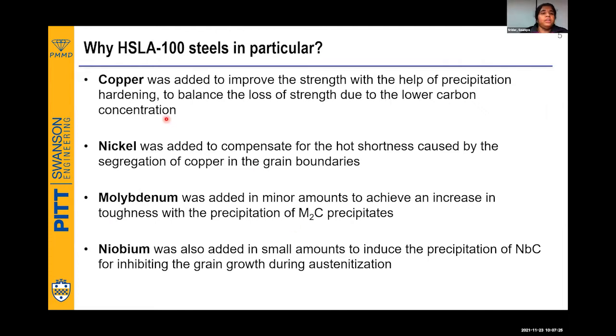And for that, the main addition is copper first. So copper is being added. That's why it's a copper bearing high strength low alloy steel. Copper is going to induce a precipitation hardening by forming pure copper precipitates, or sometimes even called clusters. So this is going to balance the loss of strength due to the lowering of the carbon concentration. Now, it's like a nested problem. If you reduce the carbon, the strength is gone. Now you're adding copper to improve strength, but copper is an element that segregates in the grain boundaries and causes hot cracking. And to compensate that, you add nickel.